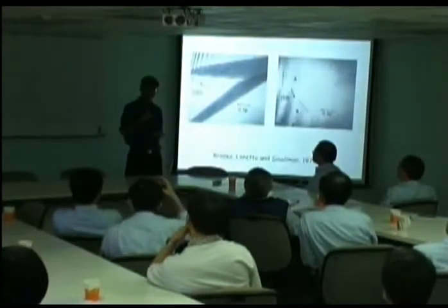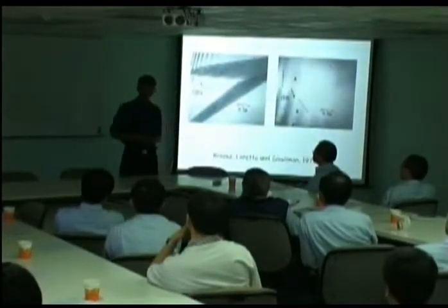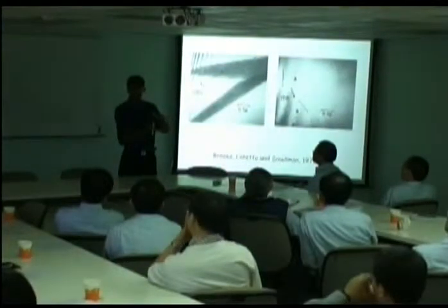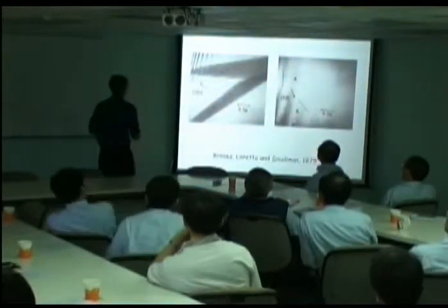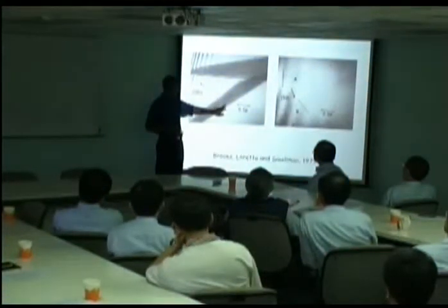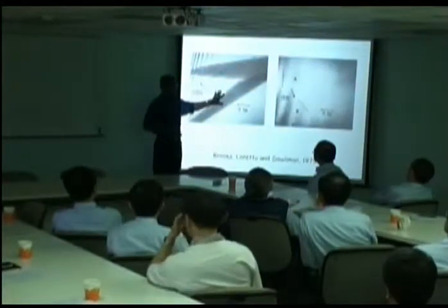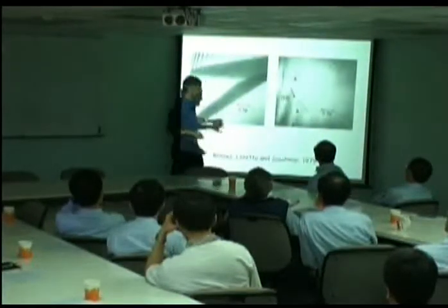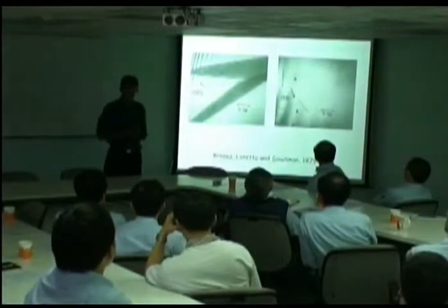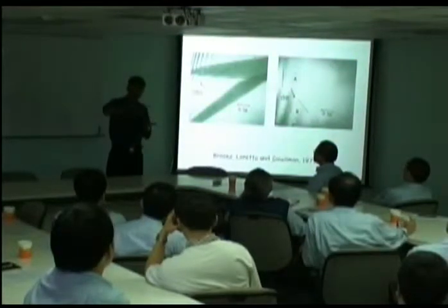Well, actually, austenite is not the most dense form of iron. Hexagonal close-packed iron is even denser than austenite. So you get a volume contraction when hexagonal close-packed iron forms. Now, in a transmission electron microscope, if I image this stacking fault using a g vector which is at 90 degrees to the fault vector, then this fault should disappear. Okay? Over here, you can see this is the same region, the fault has disappeared. Right? But notice, it hasn't completely disappeared. You can see some residual contrast here. That residual contrast comes from the volume change.